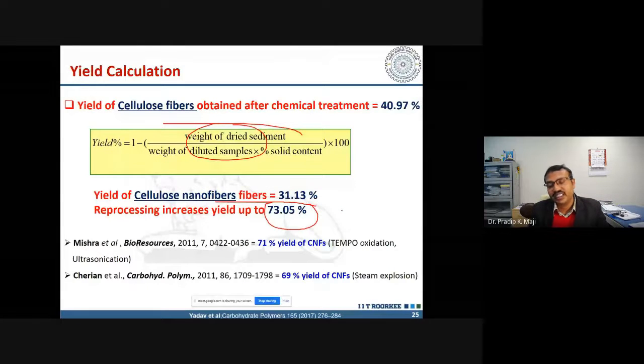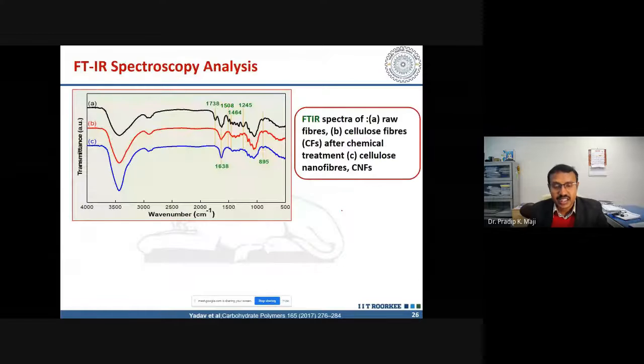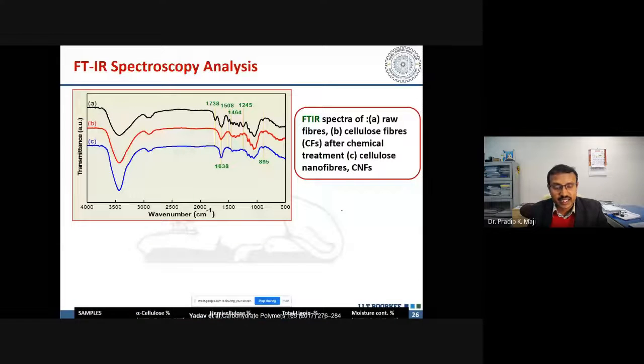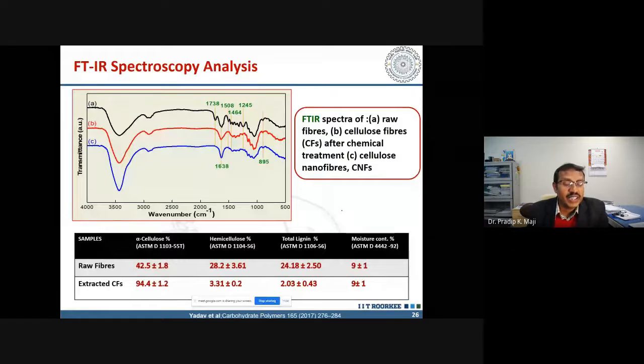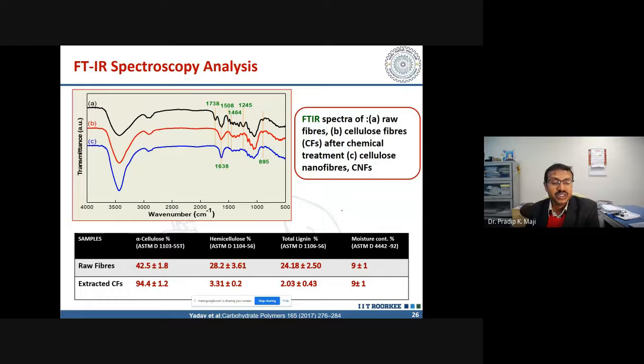Pure cellulose material - we have checked the purity of the material, comparing the raw material and extracted cellulose fibre by ASTM method. We found almost 94% purity of the cellulose, estimated by the ASTM method.